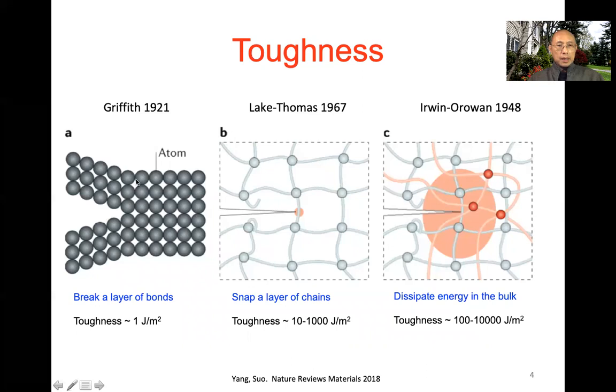Griffith considered glass as a model material, silica. So here is a glass, just a simple model picture. You have an atomic bond between these two atoms. When a crack comes along, the crack only needs to cut one layer of atomic bonds. All the other atomic bonds remain bonded and material is elastic. As a result, because you only cut one layer of atomic bonds, the toughness is very low. This is an energy per unit area of a crack, just about 1 joule per meter squared.